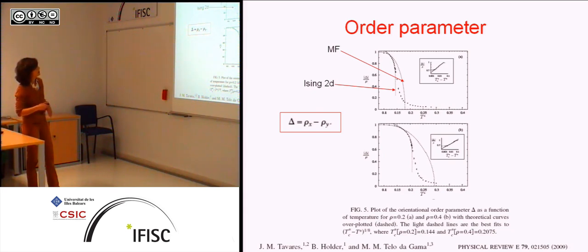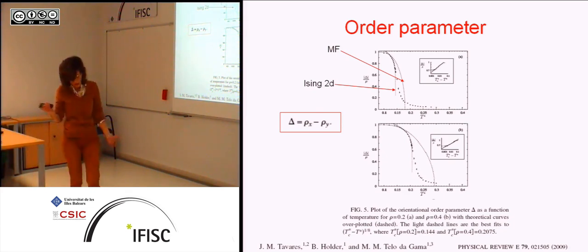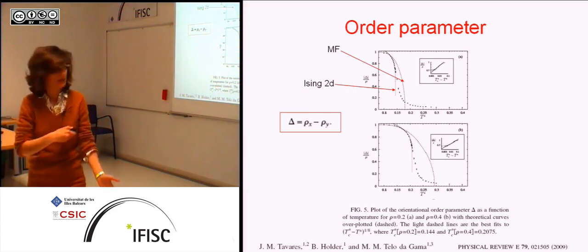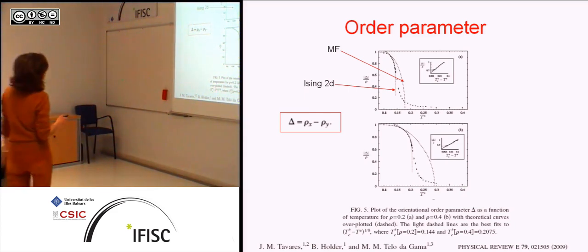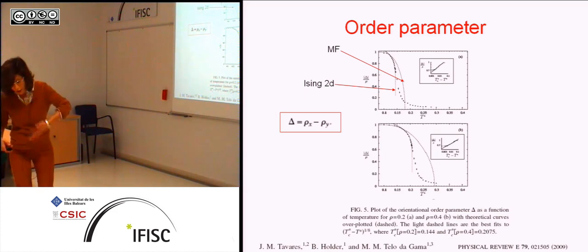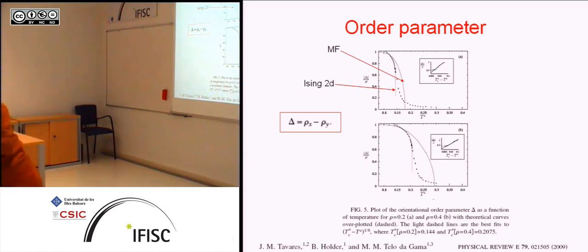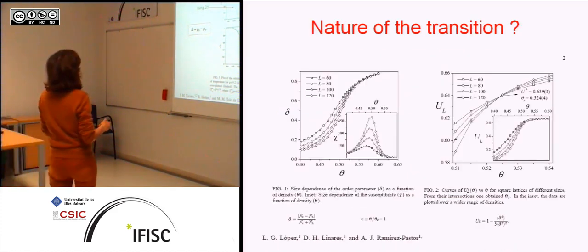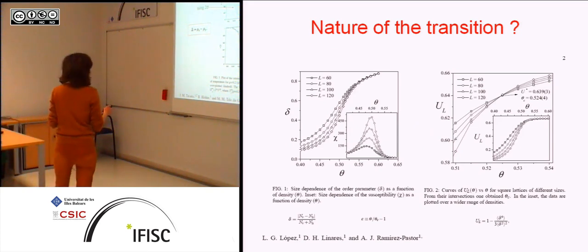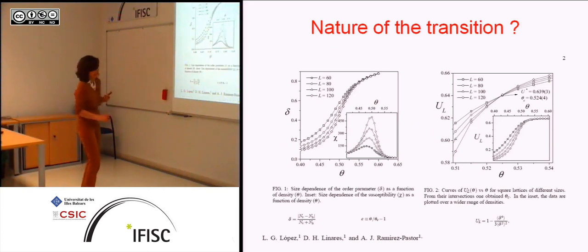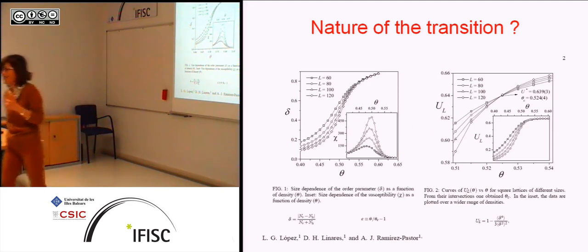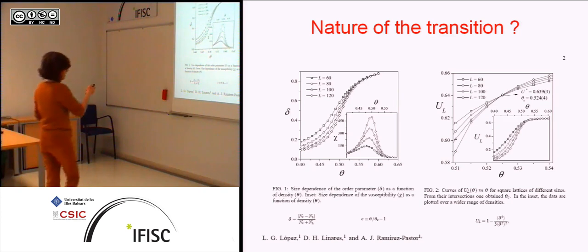This is the mean field, which is pretty lousy here, it had to fail somewhere. And these dotted things are what we expected. I mean, we assumed Ising criticality, and we just assumed that the polydispersity did not affect the order of the transition, and the fit did seem pretty good. Except the referees, I think they were the referees, because this paper came out almost exactly at the same time as ours, did the proper job, and the proper job was, I think I'll go to the next slide.